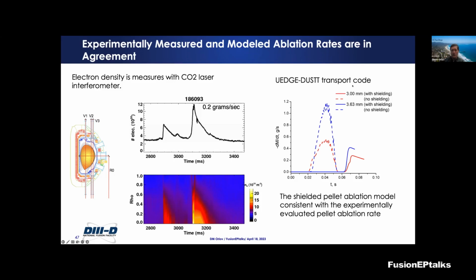UEDGE-DUSTT simulation can also calculate those things, but when we ran the code initially without any ablation shielding, the numbers were so much overestimating what we had in the experiment. You can see that for two sizes of pellets, we were getting a lot more ablation, and we had to implement some ad hoc shielding model.